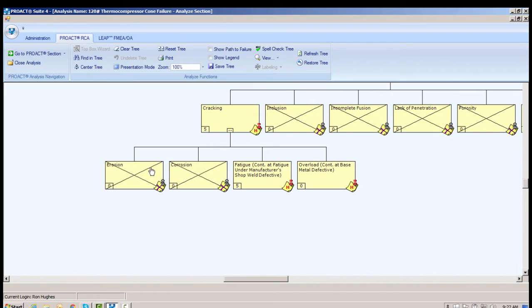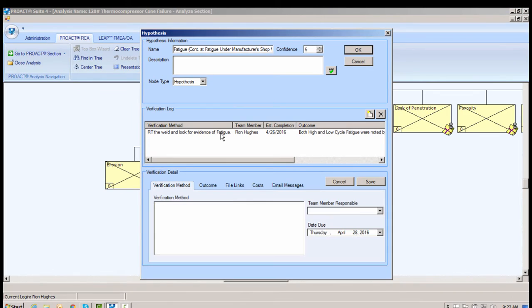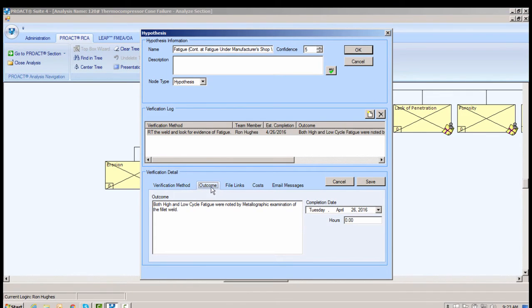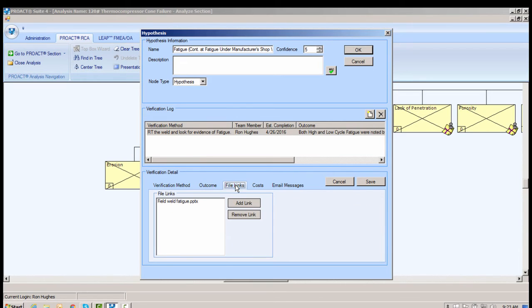Now we visually inspect the weld. There is no evidence of erosion in the weld. Also, there is no evidence of corrosion in the weld. Now notice here we got fatigue. Continue at fatigue under manufacturer shop weld defective. That means the logic below here is going to be identical to what we're going to see over here in the manufacturer's weld. But we go in and we RT the weld, and what we find is we have indications of both high cycle and low cycle fatigue.